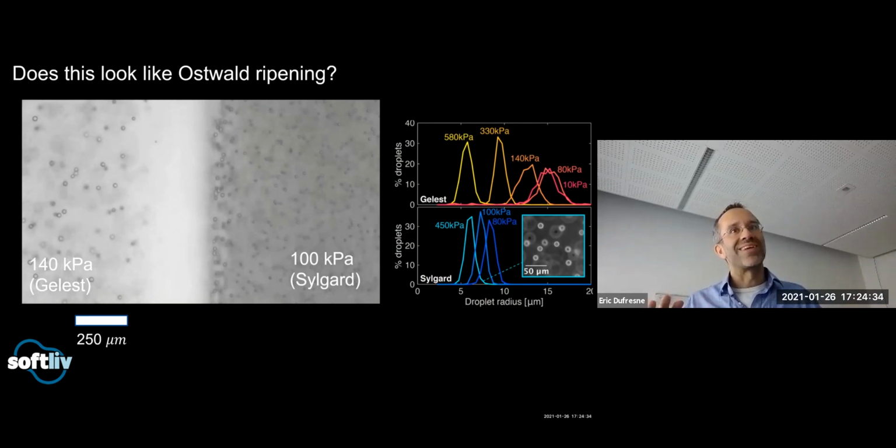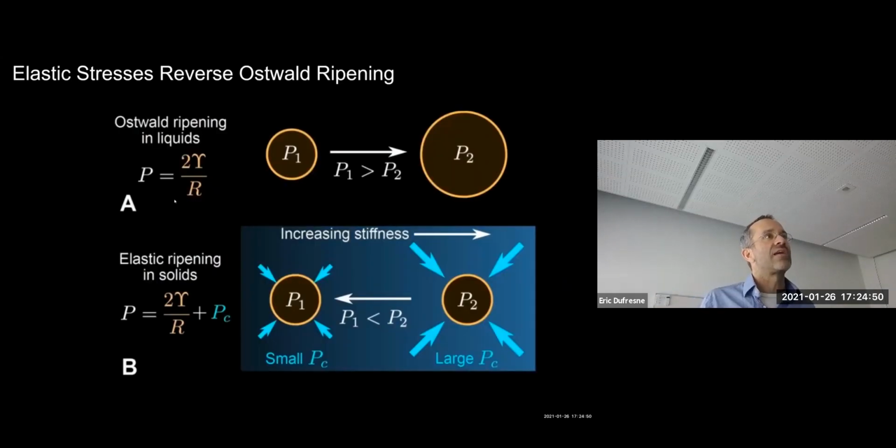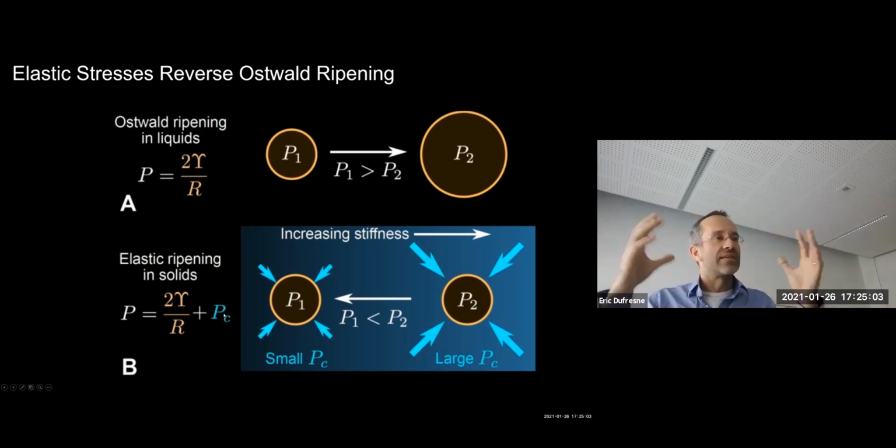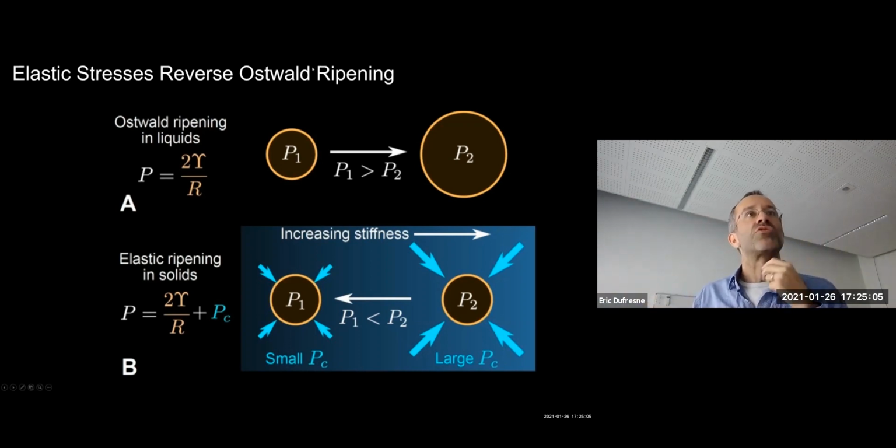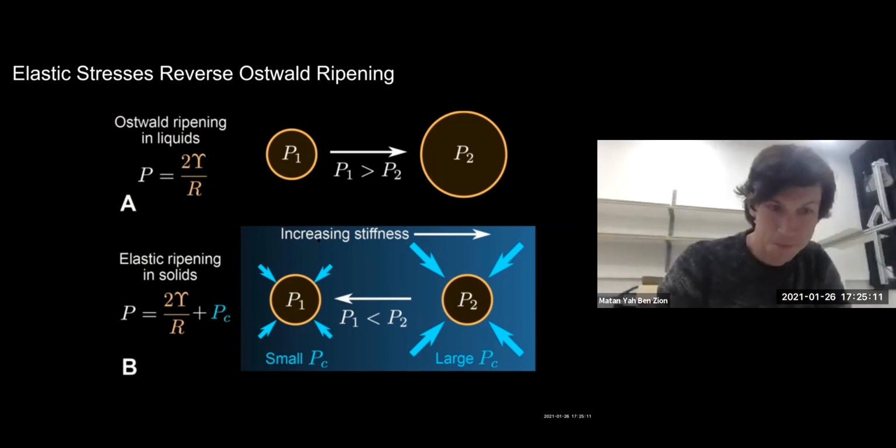droplets on the right. Okay, so in some ways this is just like Ostwald ripening because there's transport in the dilute phase of monomer driven by pressure. But the key thing is that the pressure we think is not set by surface tension like it would be in a canonical Ostwald ripening process. There's a contribution from the surface tension, but there's this extra pressure on the inside that is the network squeezing against the droplet. And we think that's what drives the transport over a long time. That's really cool. Thanks. Yeah.